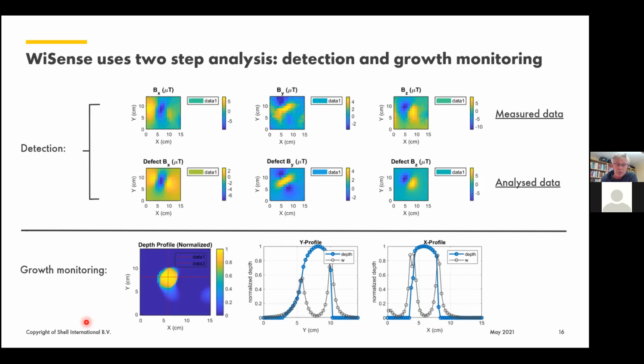Then it goes into what we call the depth profiler to monitor the growth of the indication. That is taking the data and identifying what the extent of the defect is. This is done in a graphical profile, representing the same information as in the heat map on the left. And this is on the display of the screen of the end user. Over time, and I will show you later a series of measurements of a real defect, you can see the evolution of a defect growing.